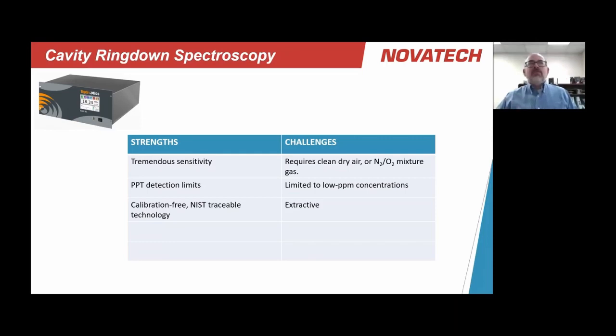So in terms of technology and strengths and challenges for the CRDS technology, the strength is the sensitivity. That ability to measure down to parts per trillion is very hard to match with any other technology. It's also a calibration-free technology, much like the TDL we saw earlier, and it's a NIST traceable technology. We can actually put NIST traceable standards within it and factor that into the correction of the analyzer or the calibration of the analyzer.